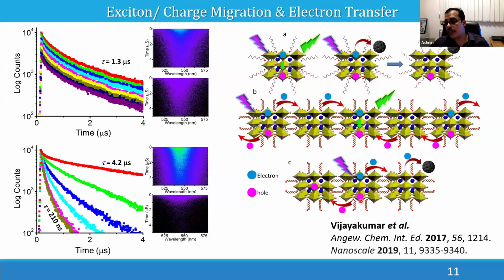But when a very, very small quantity of C60 is added, then this excitation energy migration is channeled into electron transfer, and that can be used for some other purpose, just like in a biological system, the natural light harvesting system. The initial process is light absorption, then the second process is excitation energy migration, and the third process is the electron transfer to the reaction medium, and from the reaction medium that energy is converted into chemical energy. So we reached up to the third level of a typical natural photosynthesis, that is the light absorption, energy migration, and electron transfer.